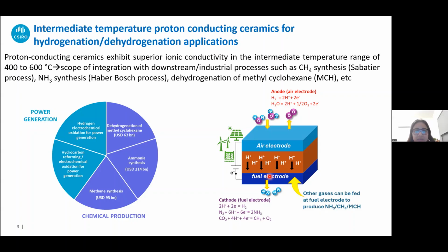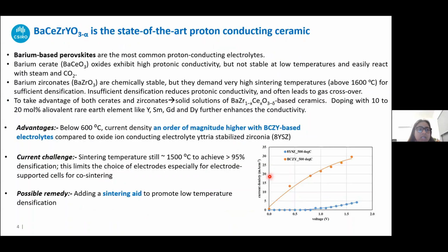Now, as simple as it may sound, there are certain material challenges, and as a result, this technology is still, I would say, at the low to medium TRL levels. With regards to the materials, the most common material used as the electrolyte is barium-based perovskites. In this category, there are mainly two different kinds. One is the barium cerates, and the other one is the barium zirconates. The barium cerates have high protonic conductivity.